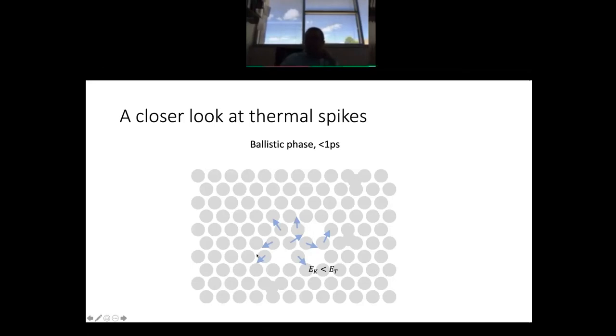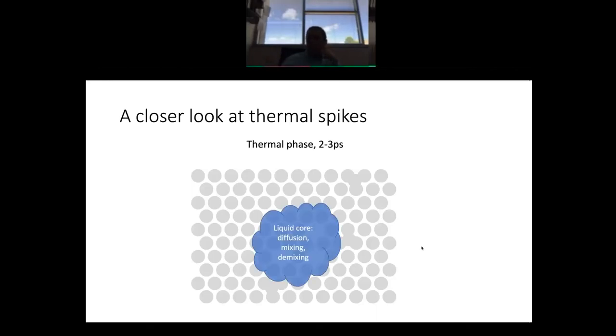All right, so what happens with these leftover atoms that have an energy that's below the threshold? Well, let's say the threshold is 20 electron volts. If an atom has an energy below that, let's say 10 electron volts, from the standpoint of solid state physics, that's still an extremely high energy. That's a much higher energy than what you need to vaporize the material. So what happens is that all those atoms that are left over basically thermalize. Their velocities very quickly converge to the Maxwell-Boltzmann distribution of velocities.